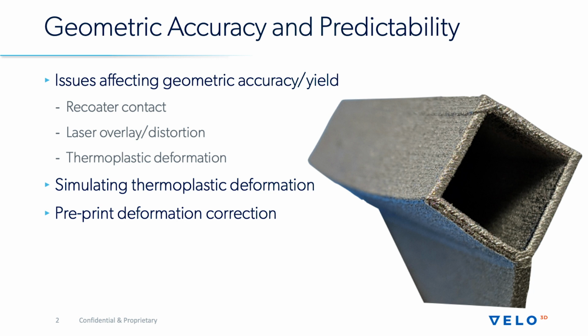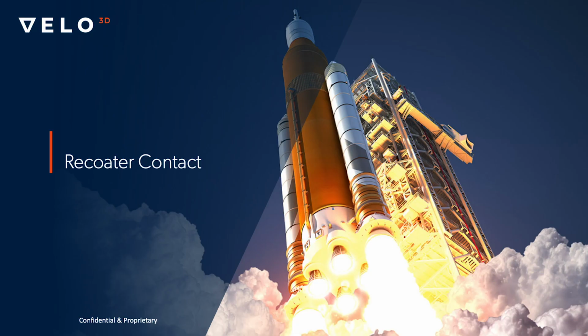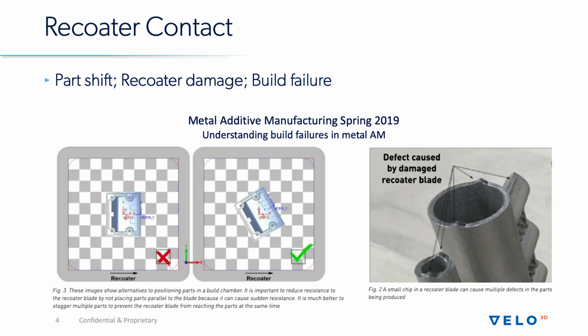build. The first place I want to start, though, is with recoater contact, because this is one of the areas which sort of jumps out most obviously as being different about the Velo machine versus other laser powder bed fusion systems. So in terms of first print yield and the origins of yield loss on first article prints, a lot of them can come down to recoater contact on conventional systems. There are multiple things that can happen when the recoater contacts a part. The first thing that can happen is that if the part is relatively weak or at a high aspect ratio, the part will oftentimes just move out of the way and the recoater will basically plow it over, which causes geometric accuracy issues and part defects.